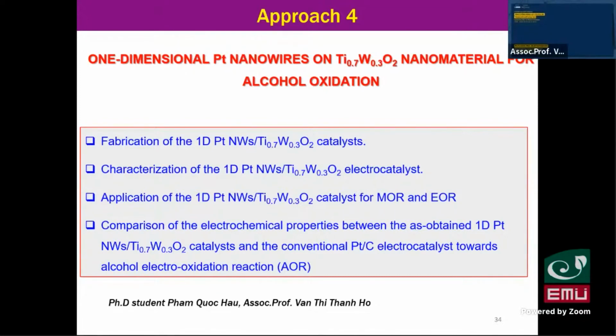For 3 years, he studied different ratios of tungsten into titanium oxide, from 0.3, 0.4, 0.5, to 0.2, to find the optimal ratio between titanium and the second metal, and applied it for alcohol oxidation.